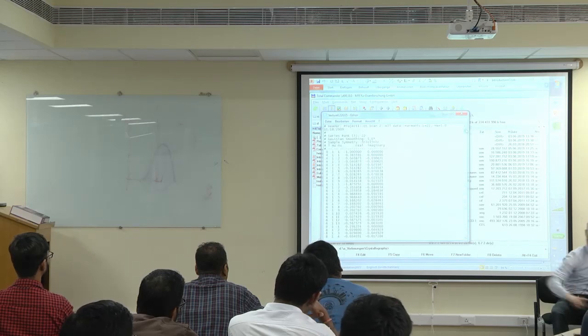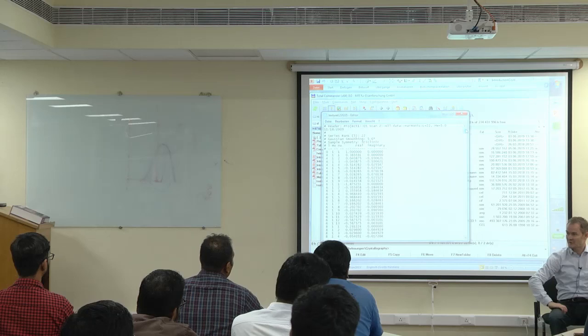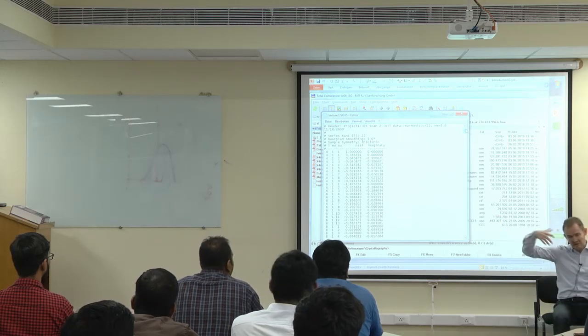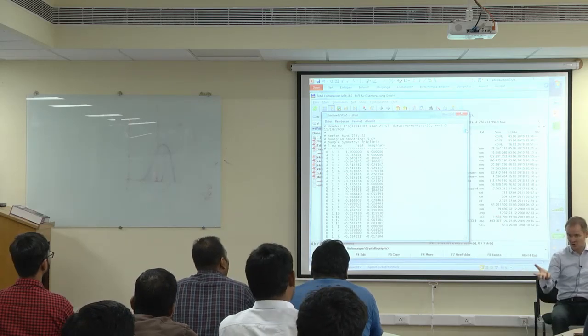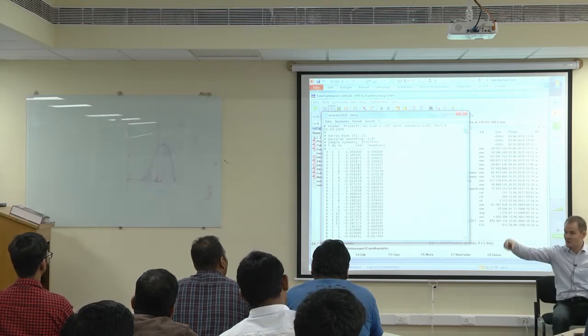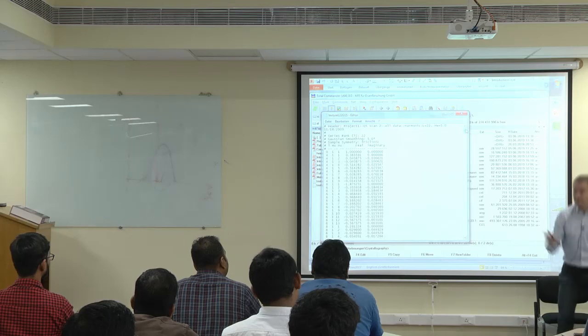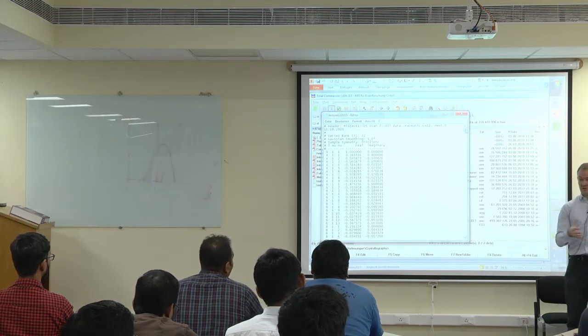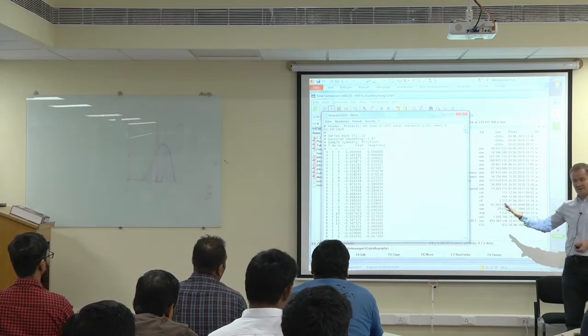And of course, it's now the question, do I need all these 700 pieces of information? Or is L equal 8 already sufficient to describe the major details? Or do I need to go to higher development degrees? Also important is, which one is the right sharpness? Is it 7 or is it 3?